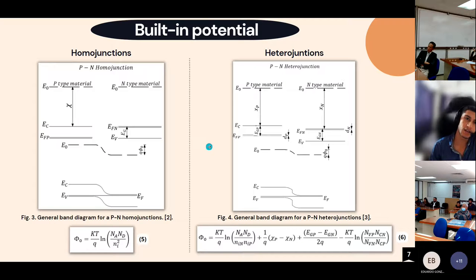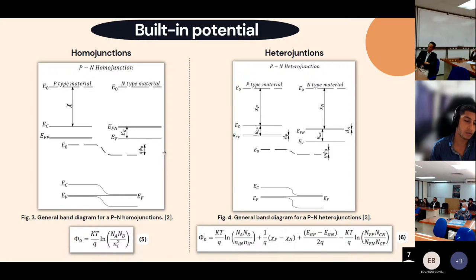It's important to know the built-in potential for the homojunctions and heterojunctions. In this slide, on the left side, we can see the expression for the built-in potential in a PN homojunction, equation number 5, in terms of the acceptor density, donor density, and intrinsic carrier density. On the right side, we can see the built-in potential and the band diagram for heterojunctions.